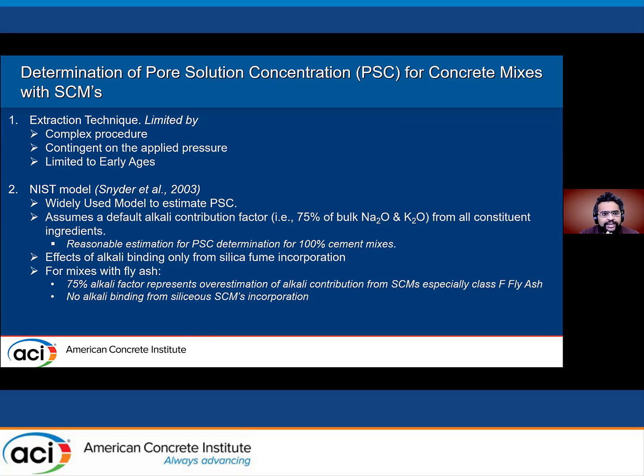So let's look at some of the techniques that are currently available to determine the pore solution concentration of concrete mixes, even with the SCMs. When we are referring to pore solution concentration, we are generally referring to sodium and potassium concentration. The extraction technique is one of the most common approaches, but it's a highly complex procedure, limited to very early ages. There are extremely few studies which have reported extraction values up to ages like 56 and 90 days. But at the later ages, the dissolution of alkali in pore solution increases with the applied pressure. So at the higher age, the more the pressure applied, we get artificially high concentrations, which is also a factor to be considered.